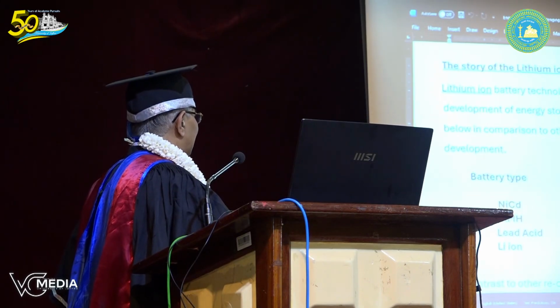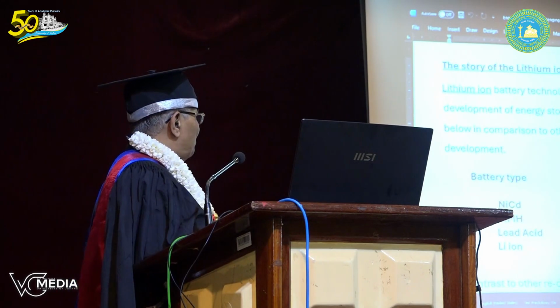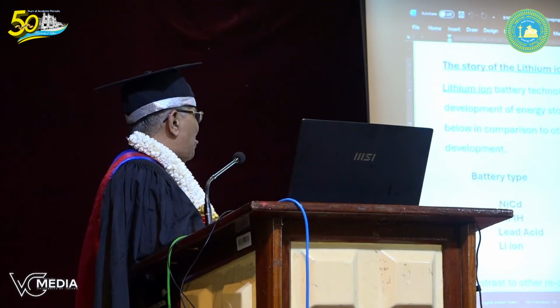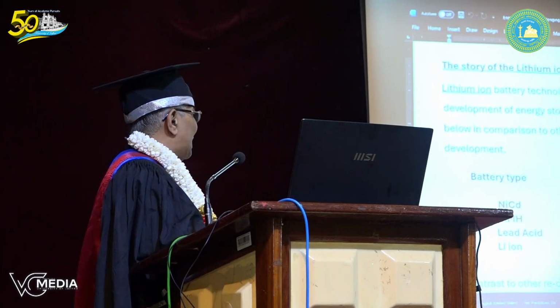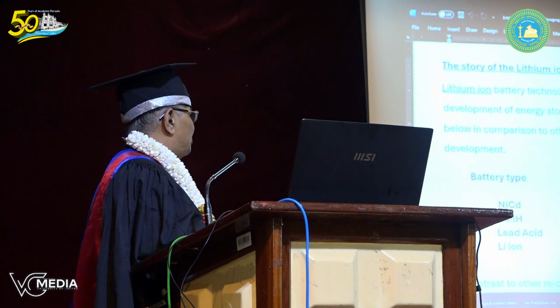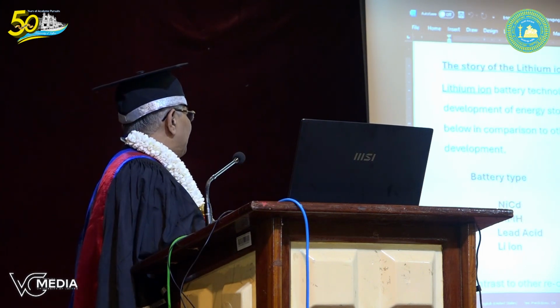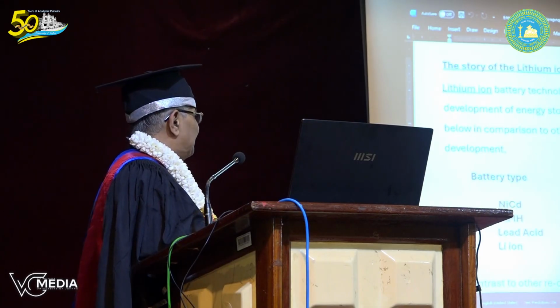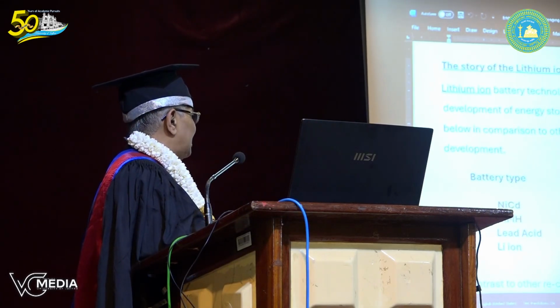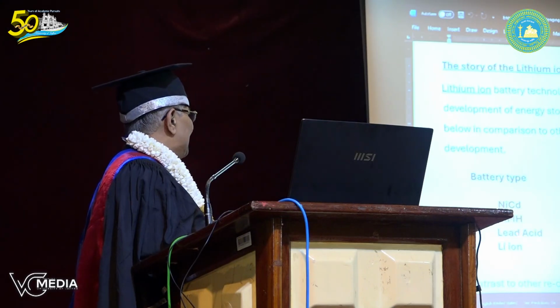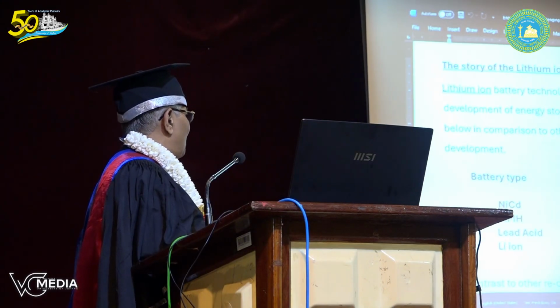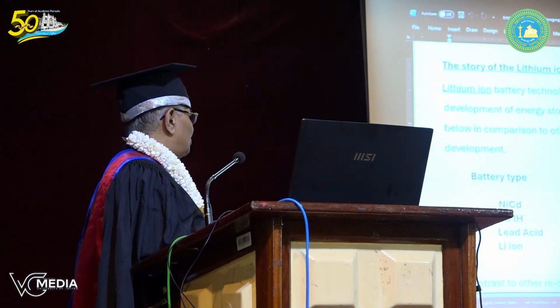Just to summarize, the nickel-cadmium battery has a voltage of about 1.2, an energy density of about 60 watt-hours per kilogram, fairly low, and a cycle life of about 2000, these being average values. Nickel metal hydride, a rechargeable battery again, has 1.2 volts, about 120 watt-hours per kilogram, and 1000 charge-discharge cycles. The lead acid battery has 2 volts, a fairly high voltage, but the energy density is low and the cycle life is also fairly low.